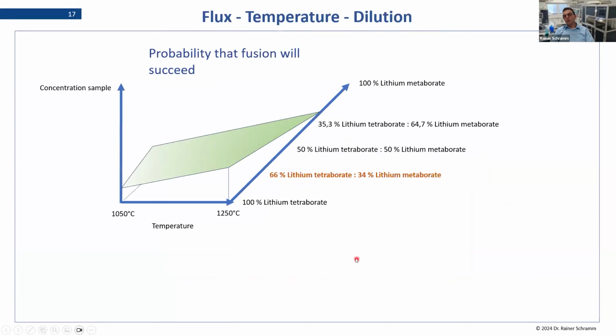Here I tried to give you a relationship between the flux on one side, the temperature on another side, and the concentration or dilution of the sample on the other side. So a three-dimensional diagram. And the plane you see here, this is just the limit: over the plane, it is not working, and under the plane, in this range, you get a stable bead. And I really try to explain a little bit how these three parameters work together.